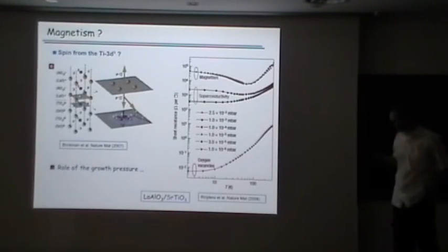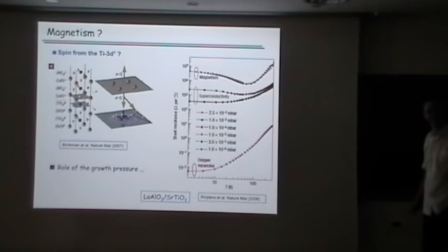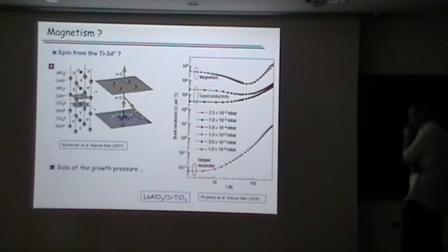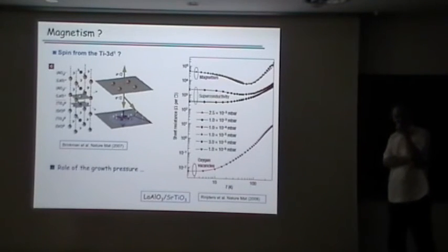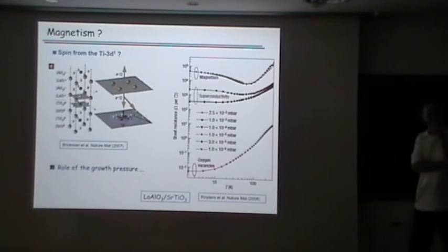Yeah. So I'm not working in this field, but I've heard some things which I have a hard time reconciling. One of them is this picture, which seems to suggest that if you make your samples the way they made them, then you should get either superconductivity or magnetism, depending on the number of oxygen vacancies. Is that the interpretation of this picture I should take away? And if so, how do I reconcile it with recent reports of coexistence of magnetism and superconductivity in the same samples?